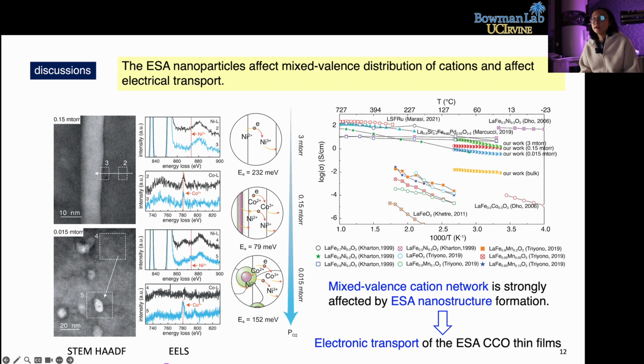We know lanthanum ferrite is an electronic conductor, and its conduction mechanism is based on polaron hopping. So polaron hopping is the electron hopping with diffusion across cations with different valence states. For example, the electrons can hop across cations like cobalt 2+ and cobalt 3+. So we introduced different transition metal cations in this LFO system, and the nanostructure may affect this cation distribution, especially their valence state distribution.